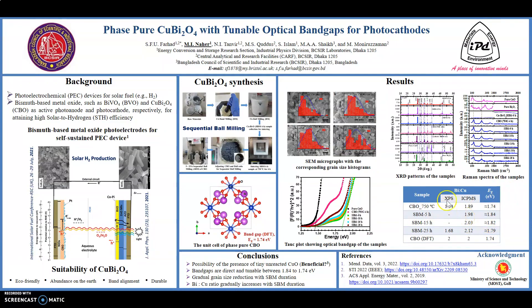We have also observed a gradual increase in the bismuth-to-copper ratio from the XPS and ICP-MS data summarized here. To theoretically explain the observation, we are also doing DFT-based theoretical study. The unit cell of CBO is shown here, and our calculated band gap shows good alignment with the experimental data. Further experimental and theoretical studies are in progress.